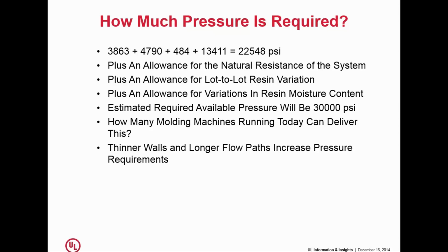And then if you're running a hygroscopic material, let's say a nylon or a polycarbonate, what you'll also realize is that the moisture content of the resin on any given day is going to influence its viscosity. If you dry a nylon to a very low moisture content, its viscosity will be higher than if you dry it to a mid-range moisture content. So it's another variable that you put into the system.